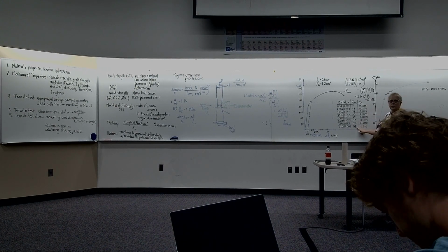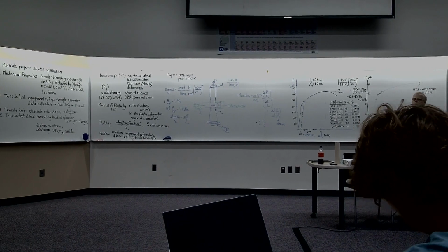Ultimate tensile strength is just the maximum stress. And I picked that maximum load at 6,100, so the maximum stress is 51 megapascals. You see that? And it's useful information to know how high this would go, but it's not useful for design. Because I never ever want to get to that level. The yield strength is a much better measure of design.